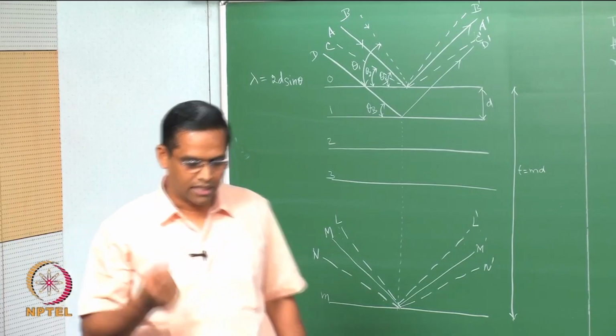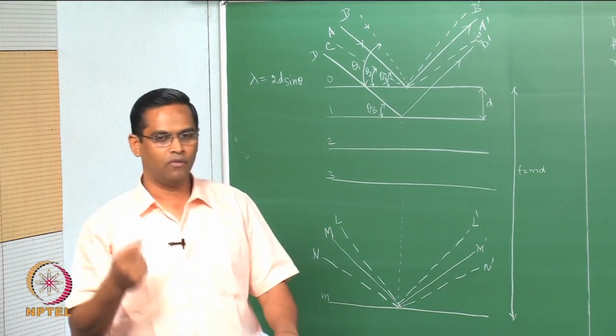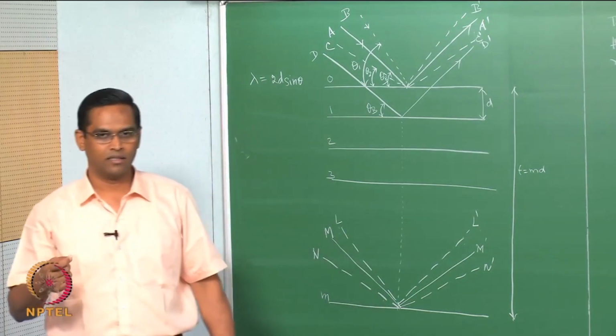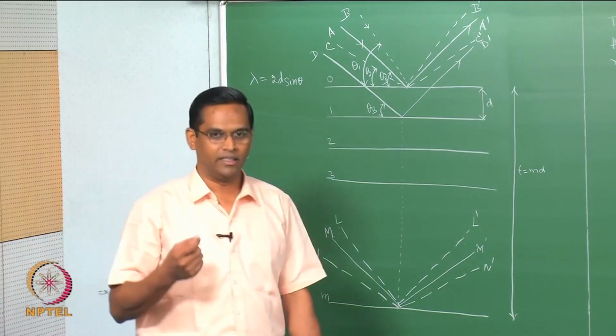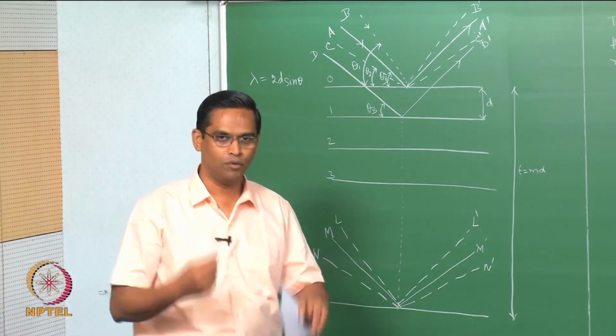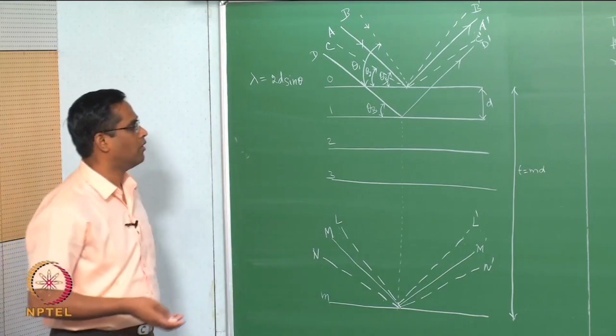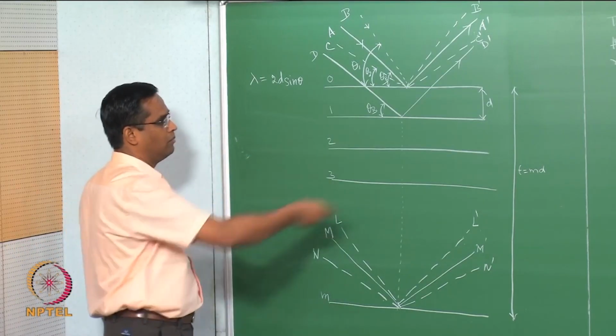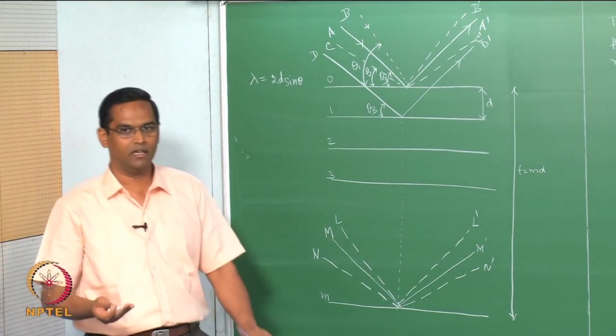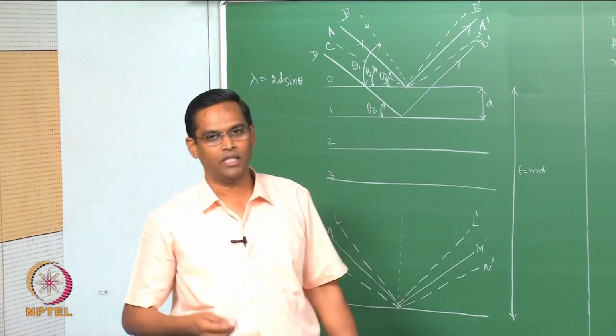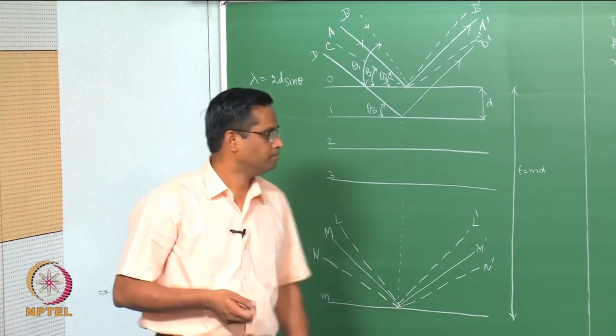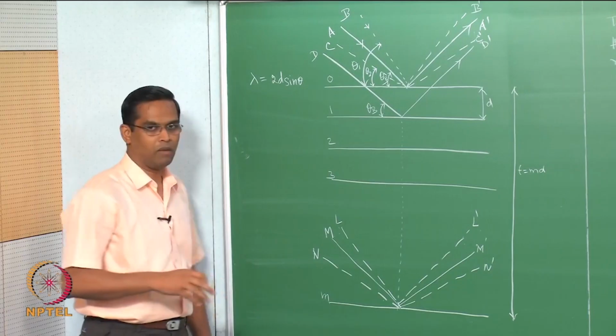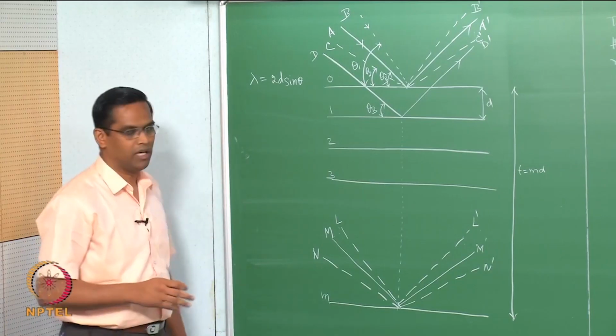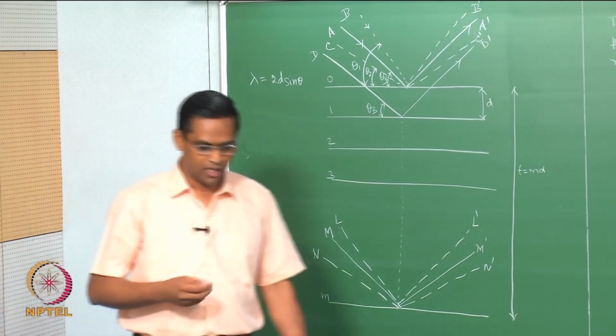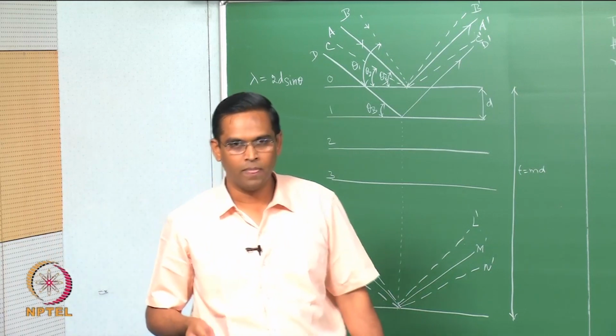So, there is a connection between the amount of out of phaseness and the crystal size. You have to keep this in mind when we talk about peak broadening, and one of the primary reasons, the physical basis for the peak broadening, is this: there may not be a plane which will completely make the path difference out of phase.